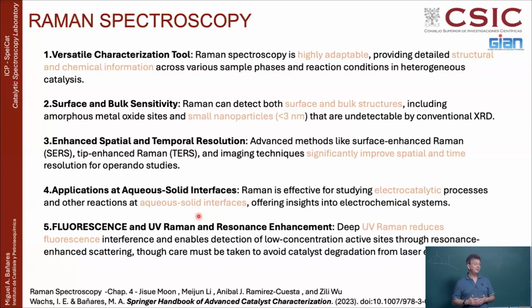And the most important thing is that it is extremely sensitive to crystalline phases, nanocrystalline, below 3 nanometer. Less than 3 nanometer, you remember, cannot generate an X-ray diffraction pattern, but that doesn't mean that you don't have a crystallite. And you can see with Raman very nicely nanocrystals of vanadium pentoxide, molybdenum trioxide, whatever, even when they are not apparent to X-ray diffraction. You don't see it in X-ray diffraction because it cannot generate a diffraction pattern, not because they are not there. So Raman will report about these nanocrystals below 3-4 nanometers, not much smaller because then you don't even have a crystal. Then you go to a few angstrom and then you're going into molecular things like just this molecularly dispersed vanadium oxide, and it will see that.